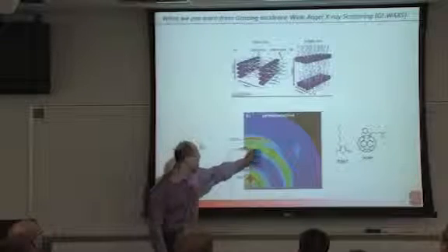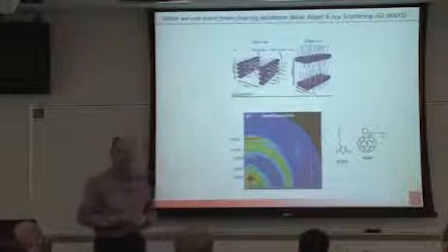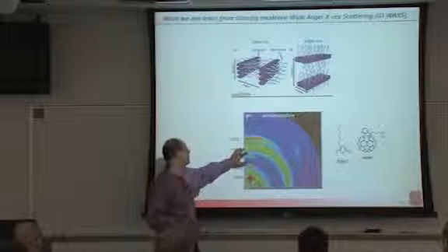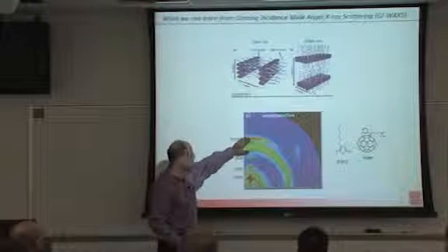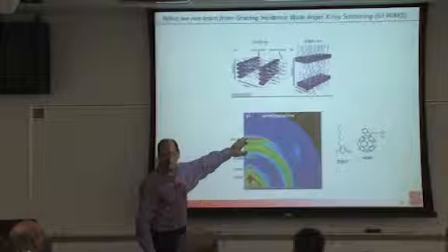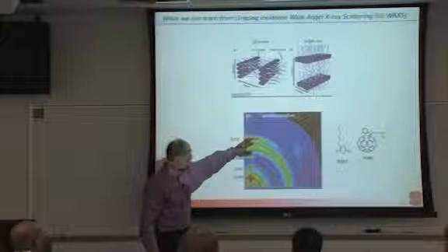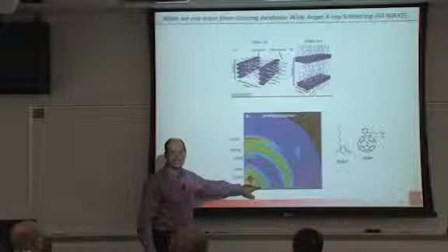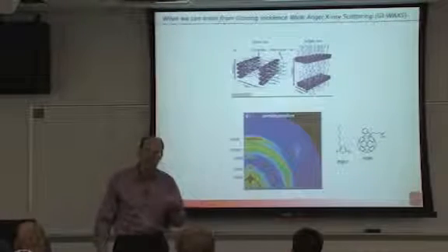the lamella. There's a PCBM diffuse halo that I can also evaluate to see how much aggregation I have. If the PCBM is completely dissolved, I wouldn't see that as well. And then here's the 101 peak, this is at larger Q, so it corresponds to a smaller spacing. So that is the pi-pi stacking direction, okay? So here I would see a component of it in the out-of-plane pi-pi stacking direction that corresponds to this amount of signal in the in-plane direction of the 100. So this is the highly ordered fraction of the polymer.